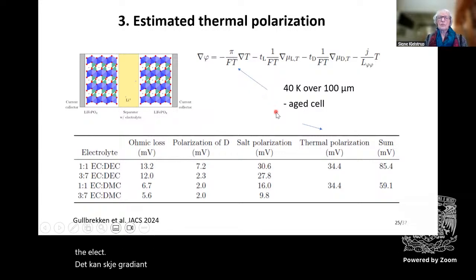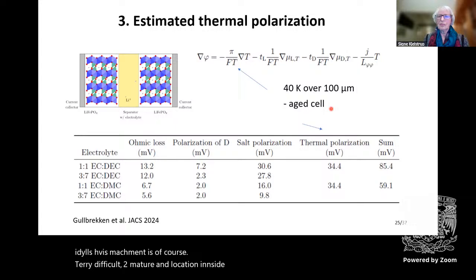And the first time we looked at the problem, we could only estimate the thermal contribution to the electric potential gradient, and the data from some aged cell indicated that there was indeed a sizable gradient. This gradient here produces a thermal polarization of the same order of magnitude as the salt, but this measurement is dubious. It is, of course, terribly difficult to measure on location inside the battery. And maybe the model is more reliable if we have reliable data. This data also shows that the chemistry plays a role here and could be used to reduce the polarization significantly.